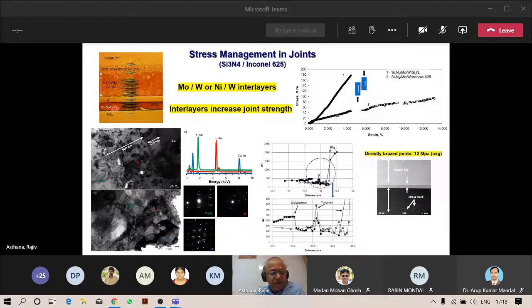So you're looking at silicon nitride on this side, copper ABA, tungsten. Then again, you have a layer of copper ABA. Next, we had a molybdenum layer. And then copper ABA, and on this side was Inconel. The Inconel has a very high expansion property, around 17 or 18 ppm per Kelvin at room temperature. Silicon nitride is pretty low, 3 to 4. So joining them directly will cause a lot of stresses. But when you put these interlayers, you're able to reduce the stress and get high bond strength.